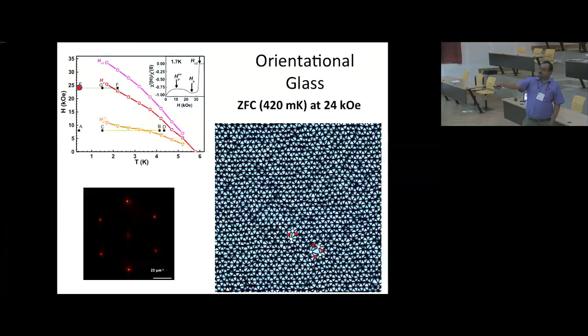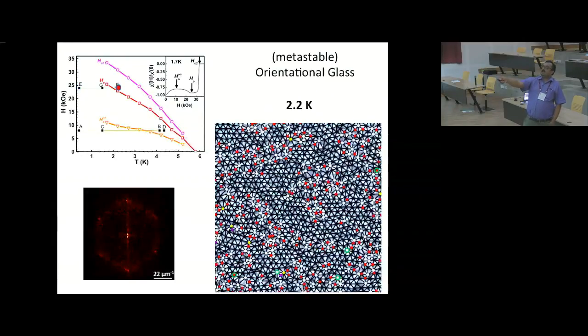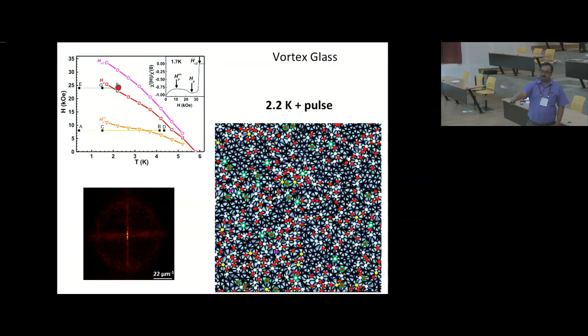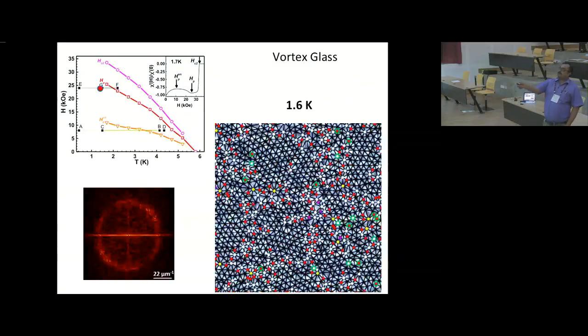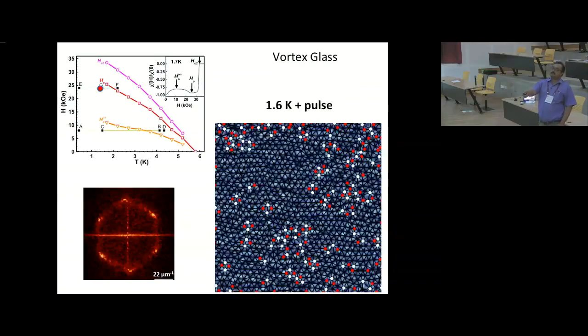Here I start already with dislocations at the lowest temperature, and then I heat it here. I have still dislocations, and my orientational order is not destroyed, though it should have been in the vortex glass because I have crossed this phase boundary. And indeed, if I shake it, I see that my Fourier transform has become completely isotropic. Similarly, I can pull it back, and I still see that it remains isotropic, but as soon as I shake it, it forms this six-fold orientational order.